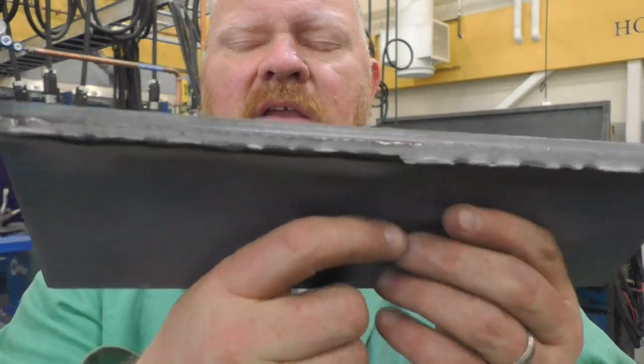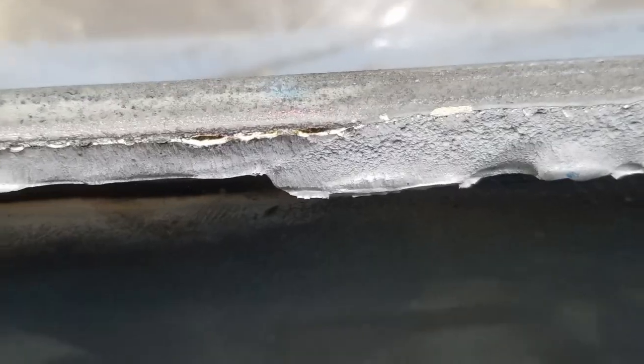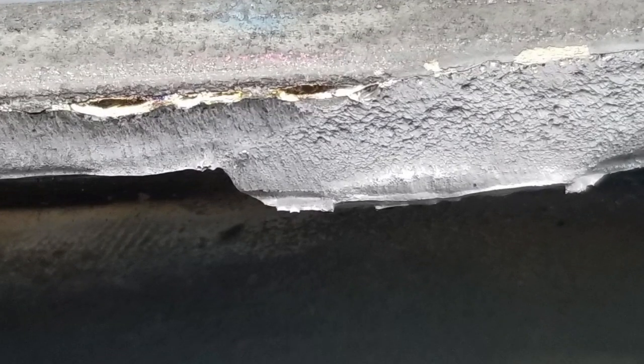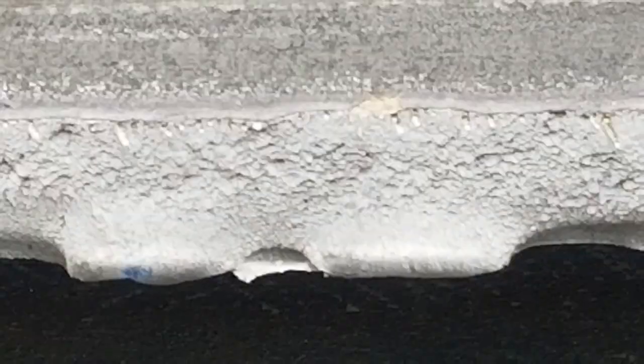And in that weld with that paint, there really are no major pinholes. If you compare the edge, there is micro porosity inside that weld, okay? Very, very small, fine pinholes. The grain structure looks a little bit different. Now, typically on a painted surface, and at the shipyard, we weld over weldable primer.